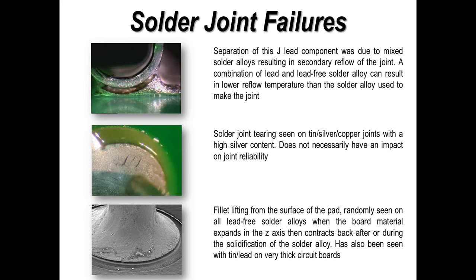Now, some things which don't necessarily cause failures, but we see them with lead-free technology. The first one I've already mentioned, which is secondary reflow, where your pin is separated from the solder. And the trick here is always look at the interfaces between the pin and the solder, and you can tell if it's a liquid separation or mechanical separation because you've got brittle fracture. So pulling the surface apart, look at them under high magnification, you can normally tell.